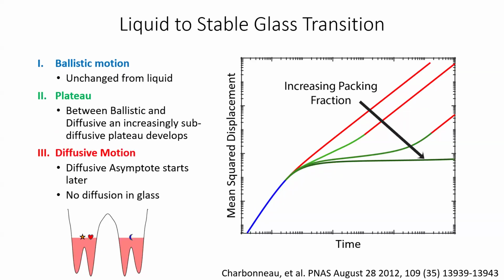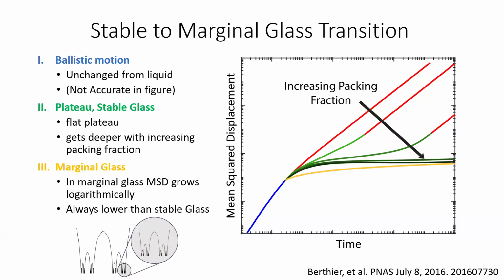The liquid to stable glass transition, we would expect to see as we increase the packing fraction, we go from diffusive behavior to getting a little bit caged and more caged, and then eventually completely caged, stuck in a plateau. And then we would expect, as we get into the marginal glass phase, this plateau falls and becomes a logarithmic growth towards the plateau.